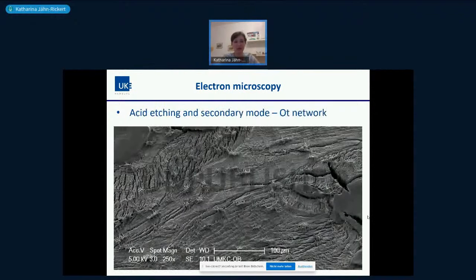Electron microscopy can also be used in secondary mode. If you have your human specimen infiltrated with the plastic polymethyl methacrylate that is generally used for histological processing, you can then apply what is called acid etching. You give some phosphoric acid on the surface of your tissue specimen, and you can etch away the bone, leaving you with the plastic that has infiltrated the osteocyte lacuna, the canaliculi, also blood vessels.